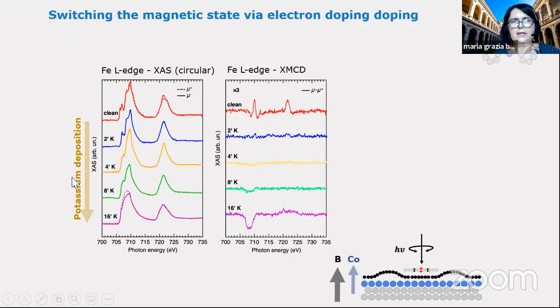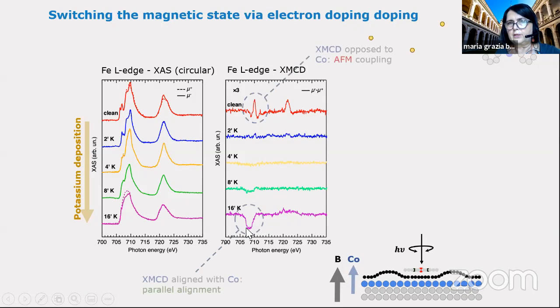So this is the potassium doping. We start from the absorption and the dichroism of the clean surface. Then we start to put potassium on, and there is a clear quenching of the dichroic signal, and then a zero signal here. But now here, you see, an opposite signal starts coming out, and in this configuration, you will have a different coupling.